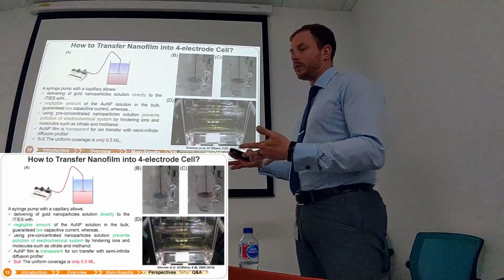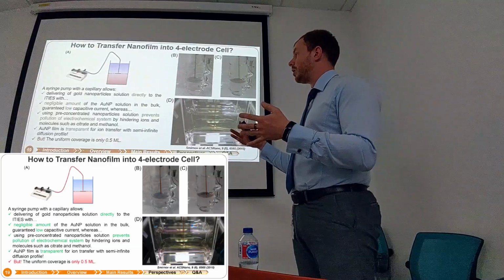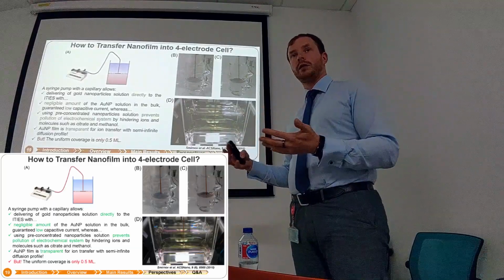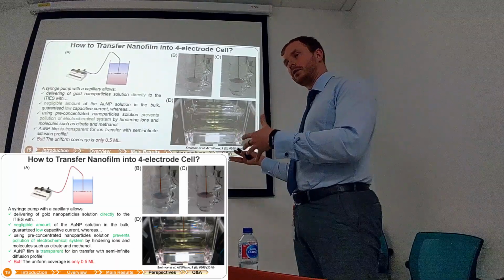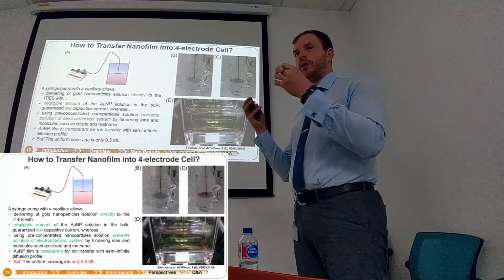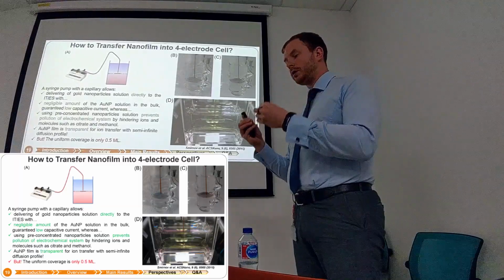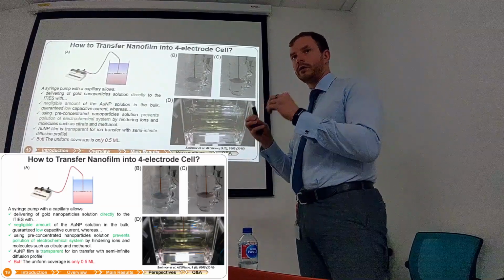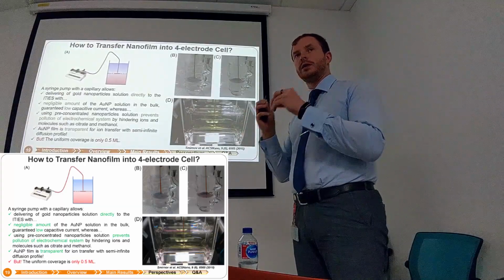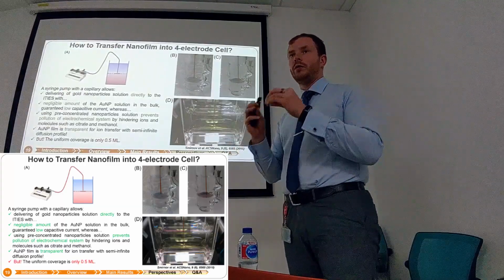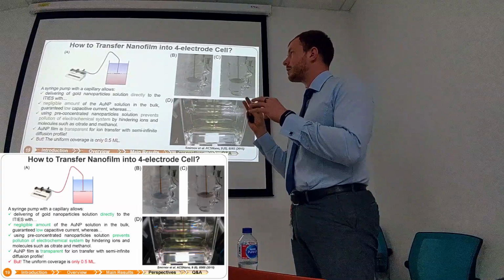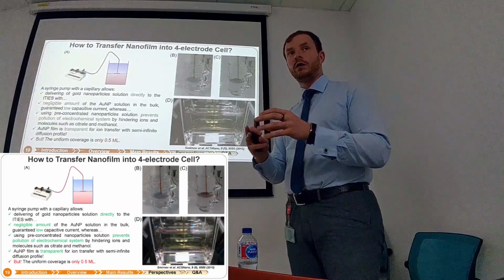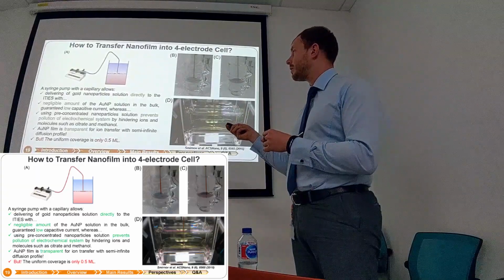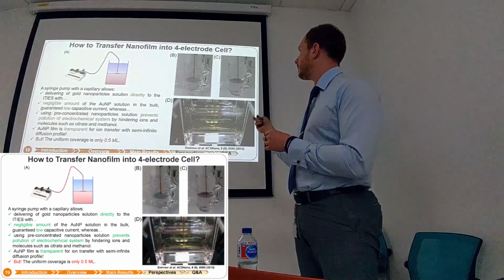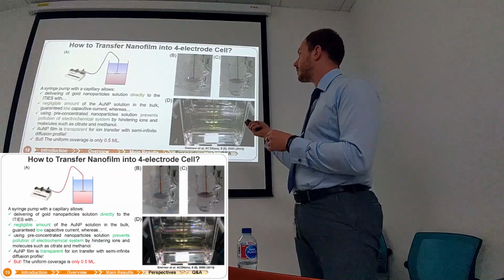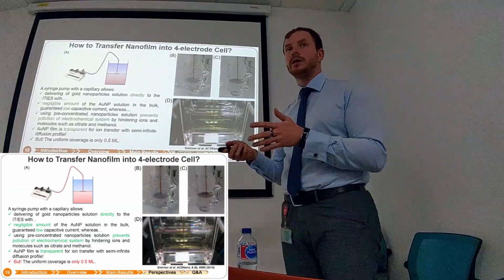We created a method to deposit film at the liquid-liquid interface. Again, coming back to the introduction, we induce locally, not globally, but really locally, this zero surface tension condition, when we have a gold nanoparticle solution concentrated in alcohol and we deliver it directly to the interface. So you can see films. It can be 2 square centimeters, it can be 8 square centimeters, it doesn't matter.